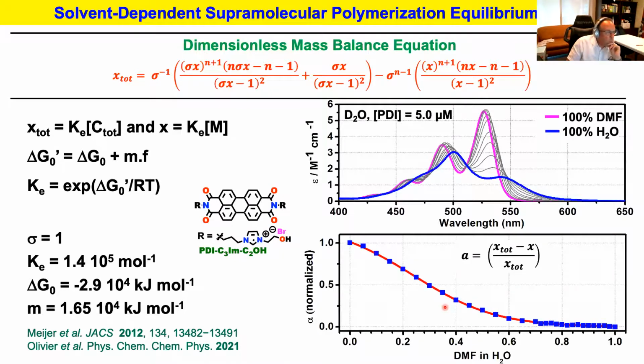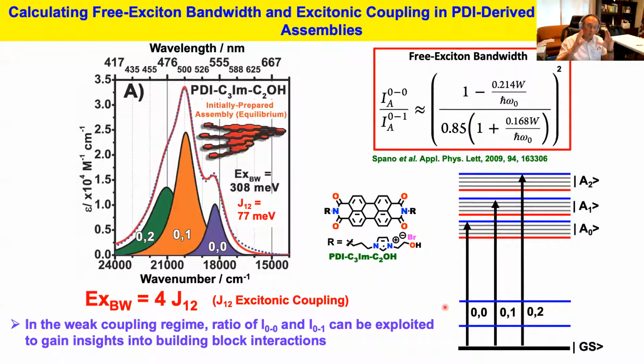Now, of course, there is a wealth of information that one can grasp out of a really simple ground state electronic absorption spectrum. And again, we are by no means a theory group, but we are very fortunate that people have made amazing contributions to this field. And one of them is Frank Spano at Temple University, who has developed a model with which we can calculate excitonic coupling that regulates the electronic properties of the small solvated aggregates in water. And so essentially what Frank has told us is that if you know the vibronic transition or the oscillator strengths of the 0,0 and 0,1 vibronic transitions, you can extract the free excitonic bandwidth, which in turn allows us to calculate the excitonic coupling.